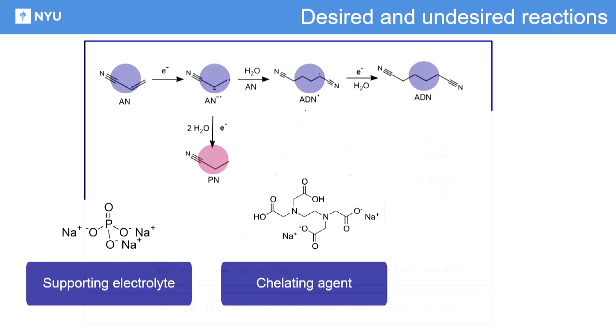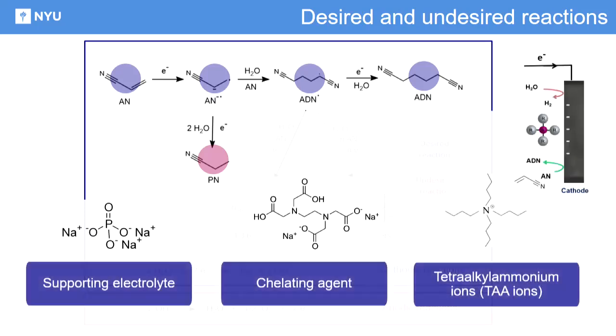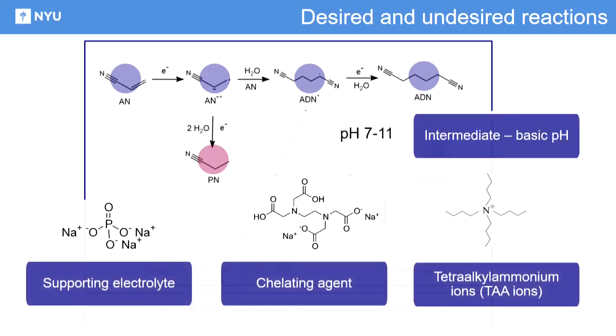You have to have EDTA because usually when you have these electrochemical cells that are undivided, your anode can corrode and those things can plate on your cathode, and that changes the selectivity of your reactants. Then you use these tetraalkylammonium ions which enhance selectivity, and they do so by going to the electrode interface, blocking water from penetrating there, and enhancing locally the solubility of your organic reactants. And overall, you need to maintain an intermediate pH, because if you go too high in pH, then you produce polymers, which you don't want. And if you go too low, then you produce a lot of hydrogen, which also eats up your electrons.